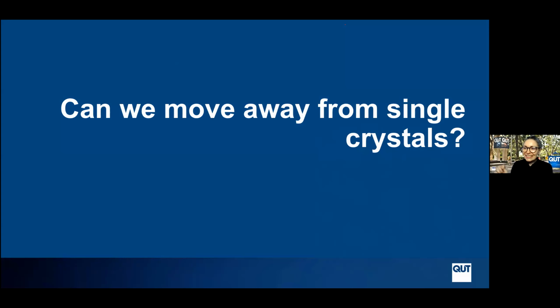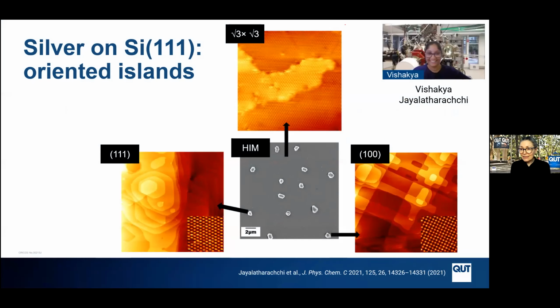This is not a logical next question, but it's one that we ended up investigating for slightly different reasons. We ended up doing some work looking at what would happen if we tried to replicate some of these experiments on silicon. That led us to this question of, can we move away from single crystal substrates? The answer turns out to be yes, and it wasn't, like I said, a question that we set out to answer, but it's one that Vishakya ended up finding a bit by accident. She was attempting to work on the silver root 3 by root 3 reconstruction on silicon 111.